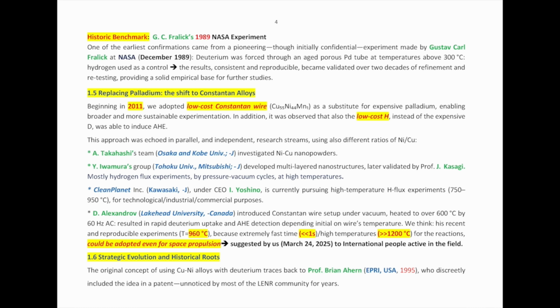So we were looking for a low-cost material, and we found Constantan matched this need. Moreover, with Constantan it is possible to use hydrogen apart from deuterium, so it always reduces cost. At almost the same time, the group of Takahashi, Iwamura, Kasagi, Celani, everybody developed independently from me. They didn't know about me. The alloy, copper-nickel, was completely different, but the conclusion was the same.